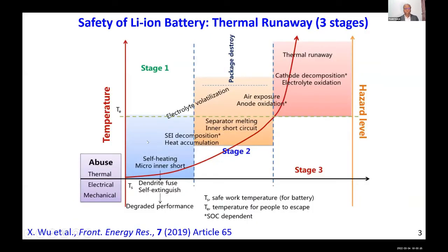This slide was also shared by Dr. Ilangovan. I would like to take this slide. So what is the cause of the thermal runaway? If you have any abuse, it could be thermal abuse or electrical abuse or mechanical abuse. What is happening is you have a cathode, you have an anode, you have a separator in between, and then electrolyte between all these cathode and anode. So what could happen because of these forms of abuse? There could be a micro internal short that leads to so-called self-heating.